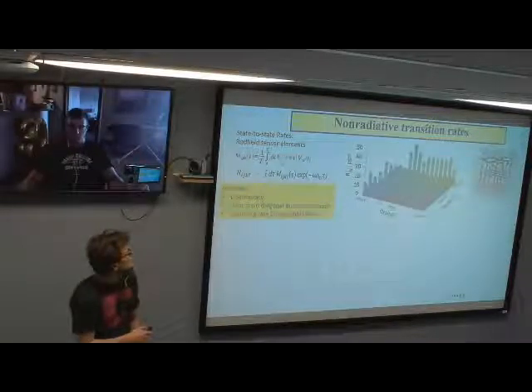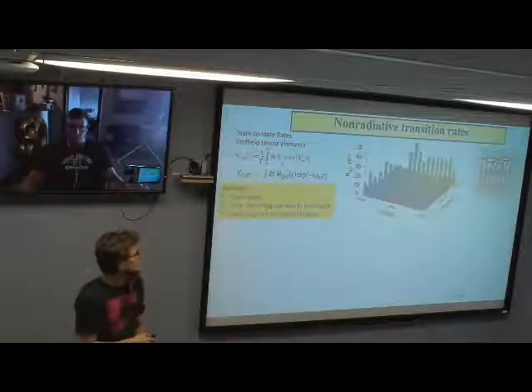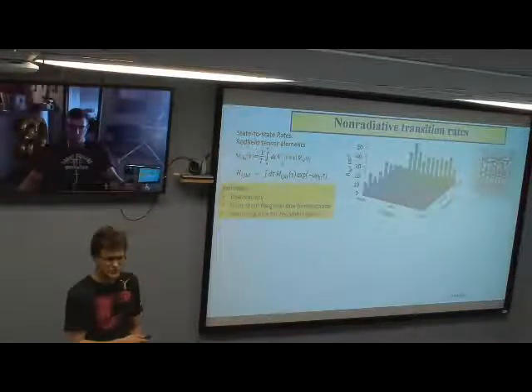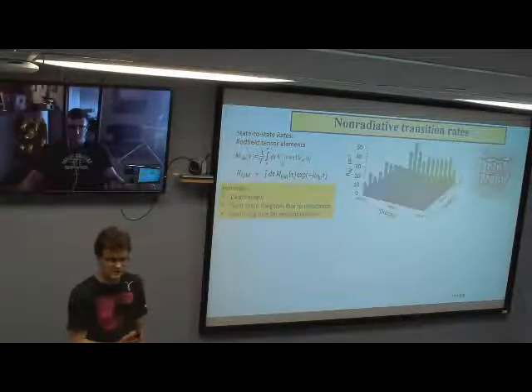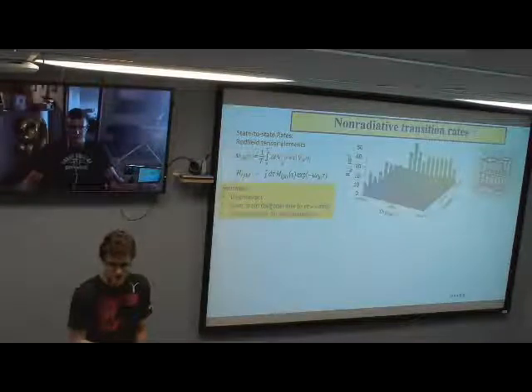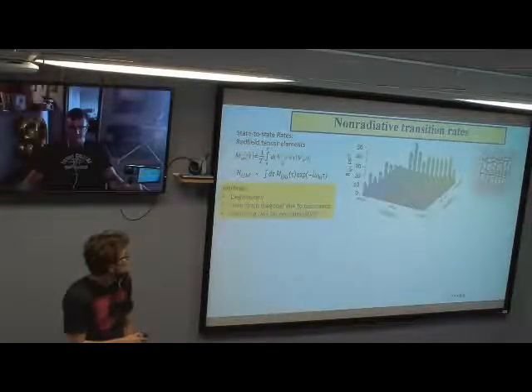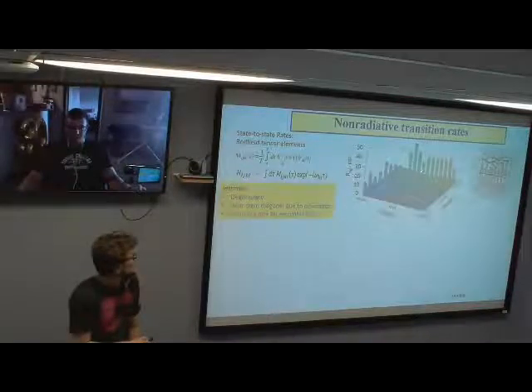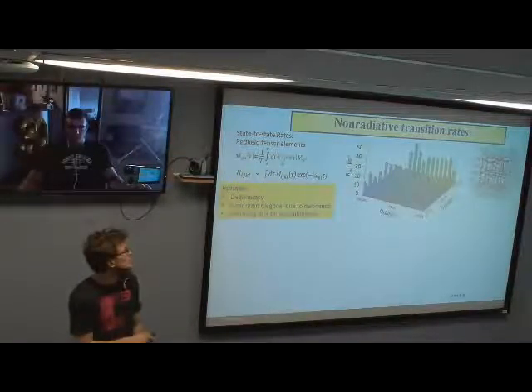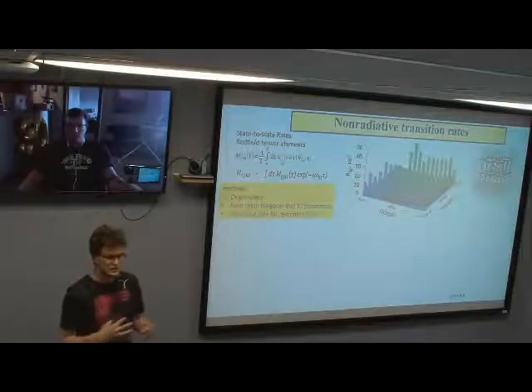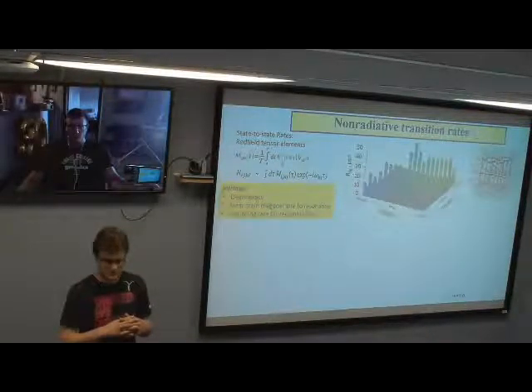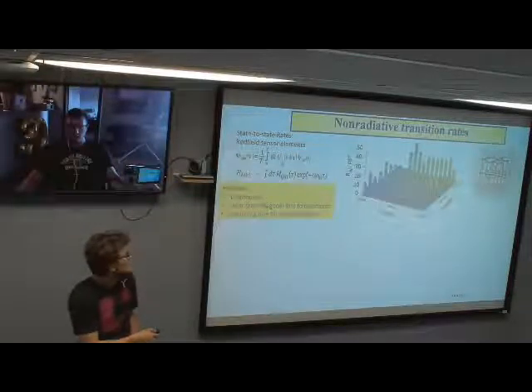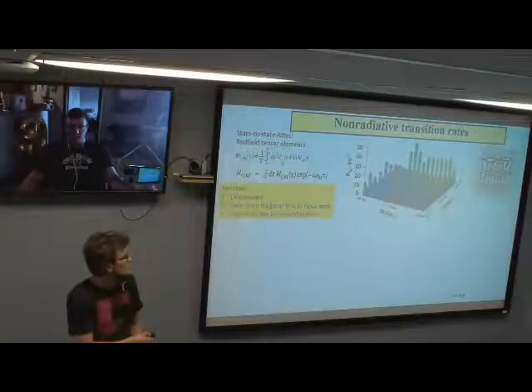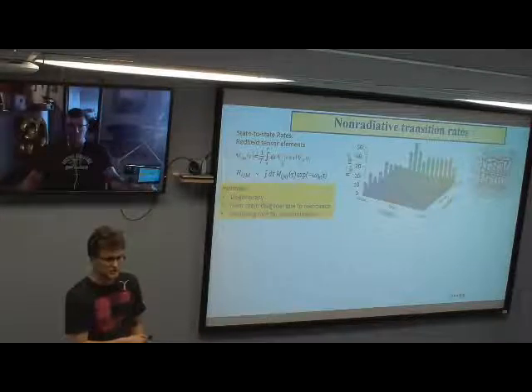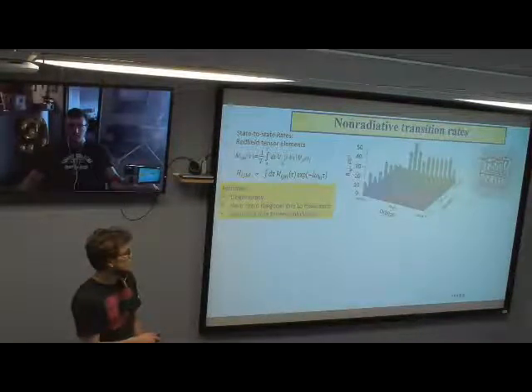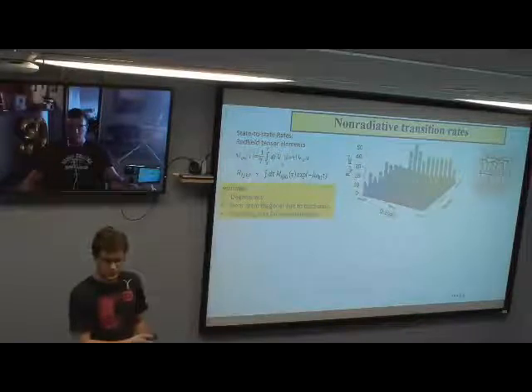And some interesting features for this state: it's generally known for systems of this crystal structure that the conduction and valence band edges are going to be twice degenerate in energy. So we see this oscillating feature going high, low, high, low, high, low. These high features would be transitions between states of the same energy, or degenerate states. And then these off-diagonal elements, which are lower in intensity, represent cooling to the band edge, or rates of transitions from HOMO minus x to HOMO minus y, and so forth.